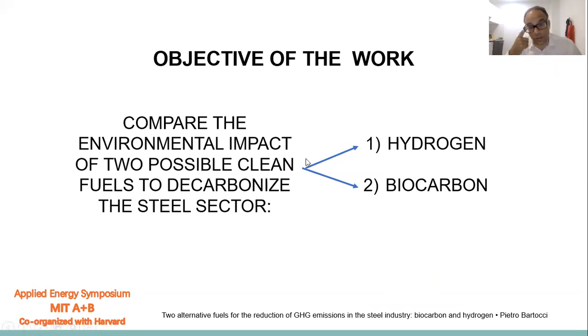What we present is a two-phase solution: the use of hydrogen and the use of biocarbon. Biocarbon can be a solid fuel for the substitution of coke, leaving the bulk of the technology quite the same. While for hydrogen, we switch from blast furnaces to electric arc furnaces, which should be fed with directly reduced iron. So we should have a first step of direct reduction of iron through hydrogen. And then we should operate an electric arc furnace, which can use, for example, carbon or the same biocarbon as a fuel and a reducing agent.